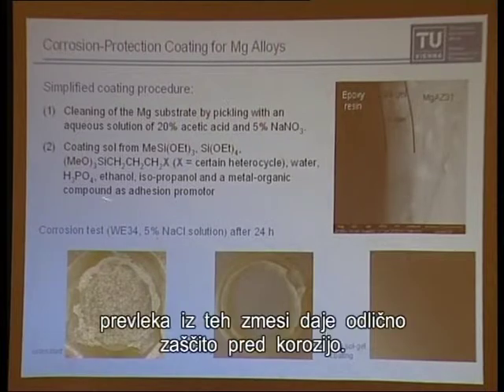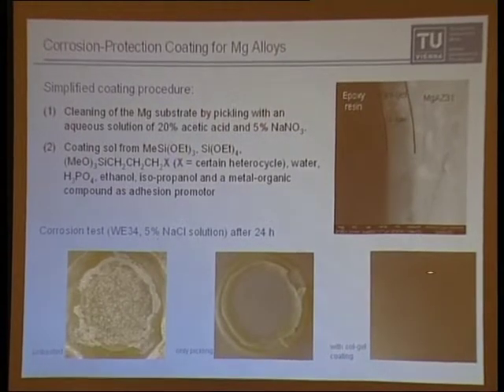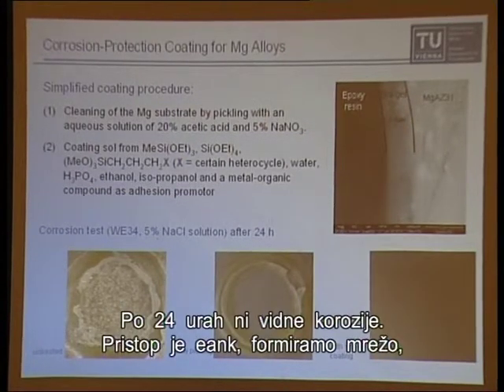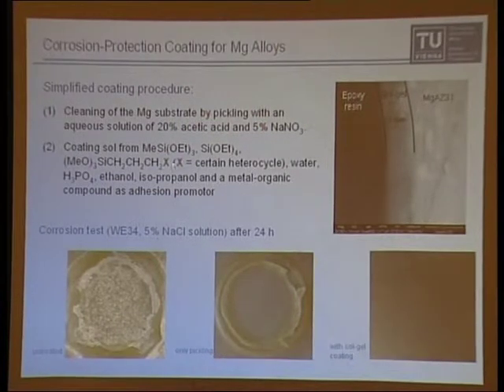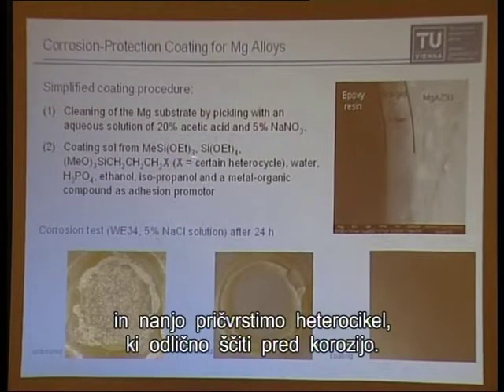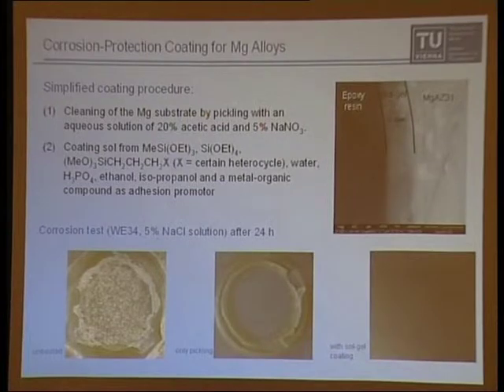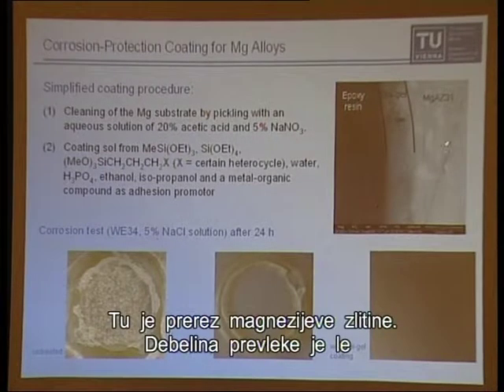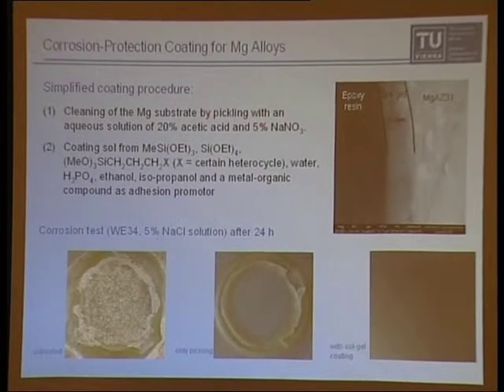But with a coating made by these compounds, by the mixture of these compounds, one gets a very good coating protection, so no corrosion after 24 hours. And you see here again the same approach, network forming reagents, and here a compound where a certain heterocycle is attached which has corrosion inhibiting properties, and having that attached to the network gives you a very good corrosion protection. So here crosscuts, a magnesium alloy, a very thin layer, 2 or 3 micrometers of these